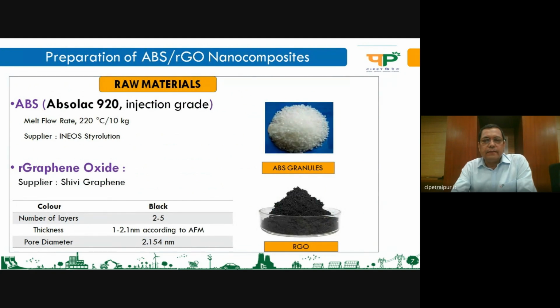So for our research activity, we have taken raw material ABS, which is Absolac 920 grade injection molding, having a melt flow rate of around 17. And then RGO, where the number of layers is 2.5 and the thickness is given as 1 to 2.1 nanometers, and the pore diameter is 2.154 nanometer.